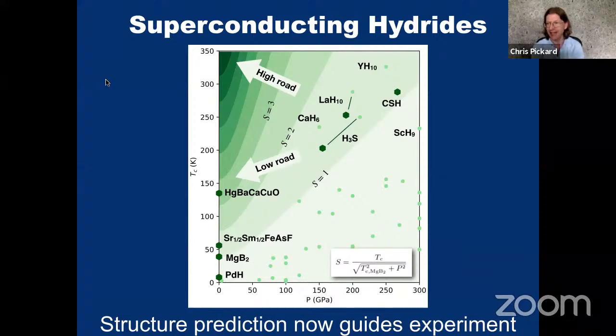So I'm using GPa and Kelvin. And so this puts MgB2 at one. So if we can find a superconductor that has an S of greater than one, I would say that's somehow more surprising than MgB2. And I think that's probably right. According to this, it shows us that the carbon sulfur hydrogen mixture is a little bit more interesting than MgB2. It's room temperature, but it's very high pressure.